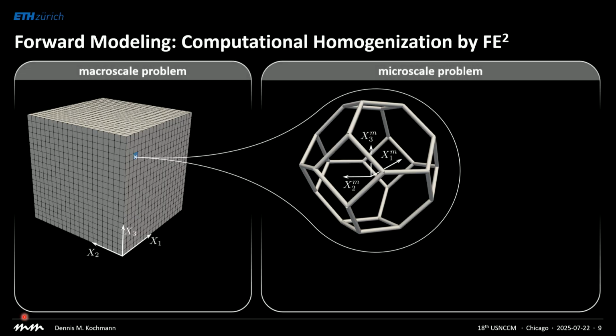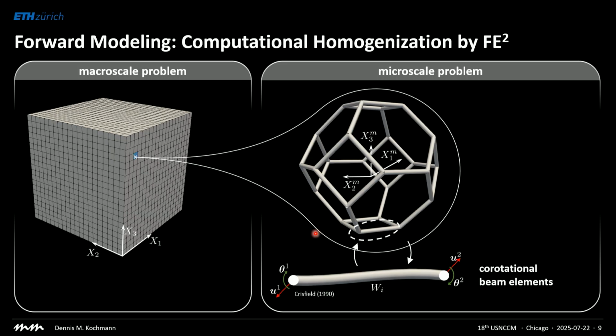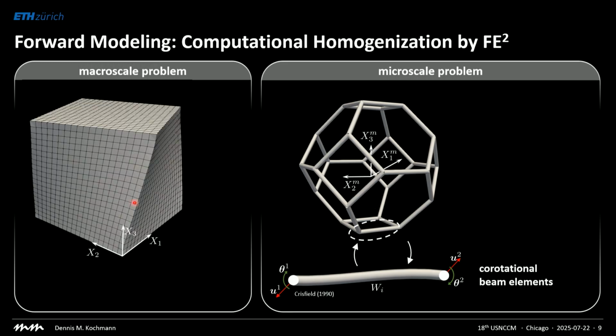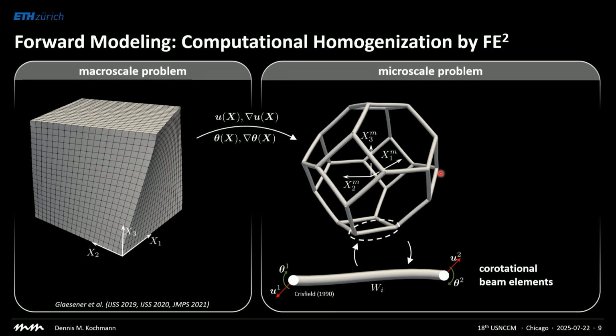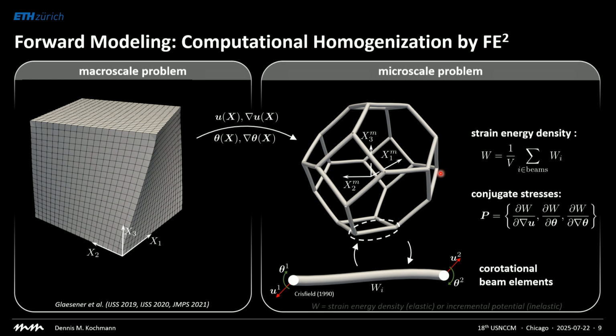On the macro scale, what we have is a macroscopic structure simulated by finite elements. On the small scale, I have a structure, which I can simulate, for example, by nonlinear beams. And now you can do FE square, but the nice thing is down here, especially when considering periodicity, you have a very small number of degrees of freedom, and this makes it readily available. So what we do now is if the macro scale deforms, and this is described, for example, by a displacement field, and we also throw in a rotation field, I'll explain why in a second, you pass those and the gradients down to the small scale, you deform the unit cell accordingly, and then, using periodic boundary conditions, you figure out what is, for example, the strain energy density in elasticity.